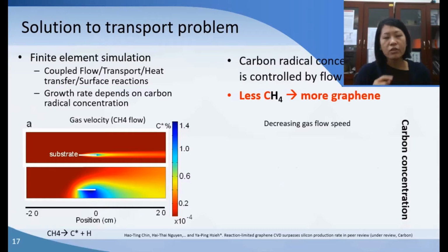We calculated every 1 million of the methane, the carbon radical, carbon precursor, there's only one carbon that actually converts into the graphene atom. So apparently we're using this very inefficiently. Every 1 million of precursor carbon that we put in, only one grown into 2D material. So we're wondering why. And so we did simulation, and we found that actually flow speed is the dominating factor. The flow speed of the molecule is very important to the growth rate of 2D material, because if you flow too fast, before the precursor got converted into useful carbon radical, it's already got pushed out. So there's no way the precursor can be grown into 2D materials.